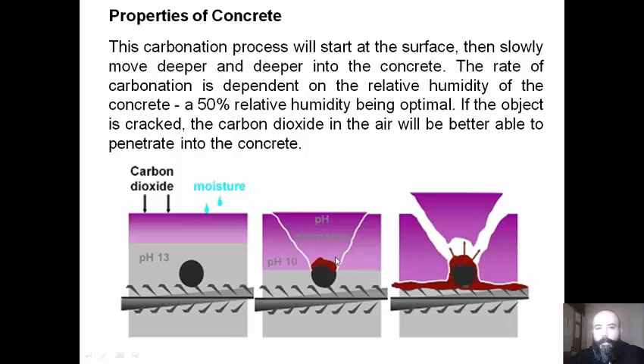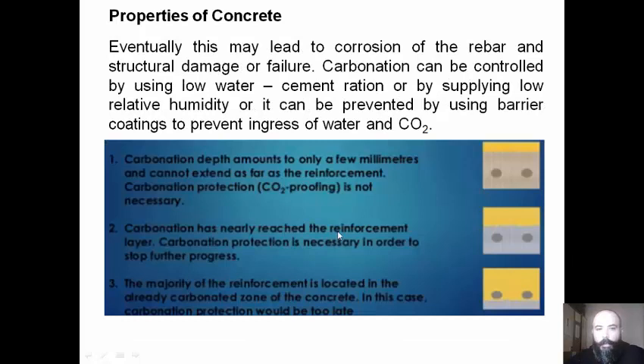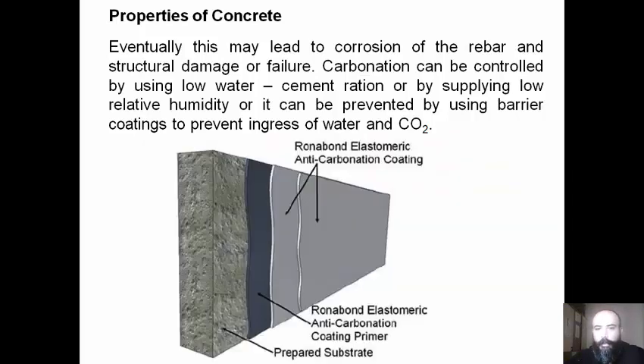The rate of the carbonation is dependent on the relative humidity of the concrete, a 50% relative humidity being optimal. If the object is cracked, the carbon dioxide in the air will be better able to penetrate into the concrete. Eventually, this may lead to corrosion of the rebar and structural damage or failure. Carbonation can be controlled by using low water cement ratio or by supplying low relative humidity, or it can be prevented by using barrier coatings to prevent ingress of water or carbon dioxide.